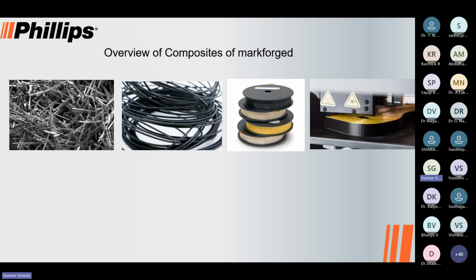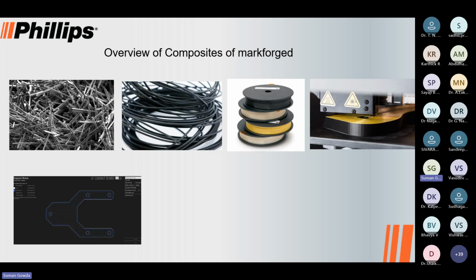And this is how the printing of a continuous fiber would happen. As you can see, the black is deposited on the boundary, whereas the yellow, which is the continuous Kevlar fiber, is being deposited on the entire part as per my end application. Because of this fiber, I am going to get a unique strength. In the image, it's the software image. If you are able to see the blue line, this is the fiber path. In this part, we have decided to give the fiber only in the boundary, whereas the infill geometry is still around 30%. So this part is now 50% lighter than the existing aluminum part, but it is still giving the same strength.